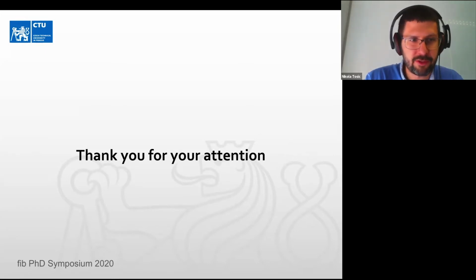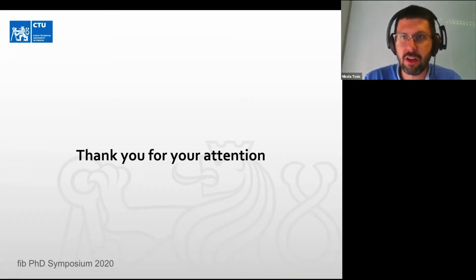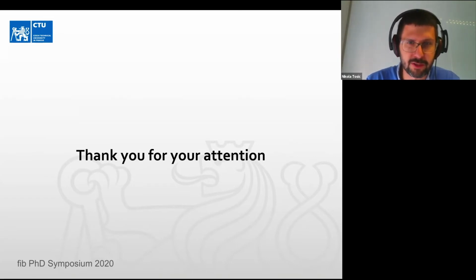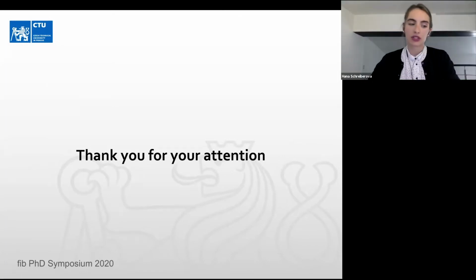So maybe while we wait for the first questions, I would like to ask, because maybe I missed or didn't understand, were mechanical properties of the concretes tested to know if they are of different strengths, seeing that, if I understood well, there were very different crack widths in the different types of concretes? So is it different tensile strength or any properties that were tested? No, in this study, we did a preliminary test with similar mixes, but unfortunately not in this one. However, the SAP decreases the tensile strength of the material a little bit, but it's not that significant.